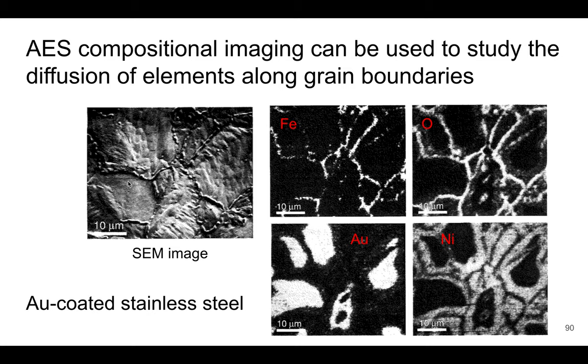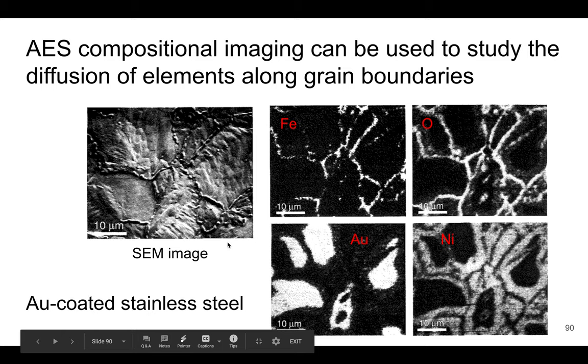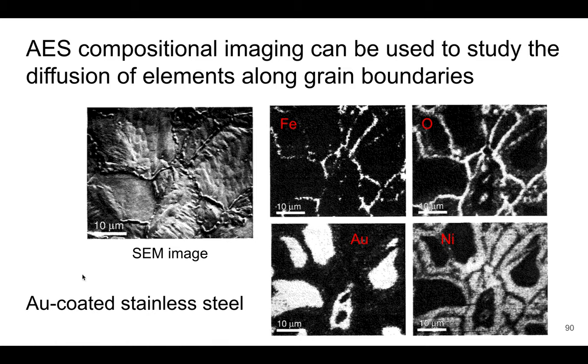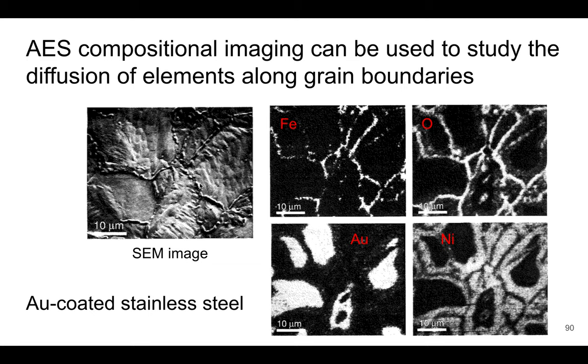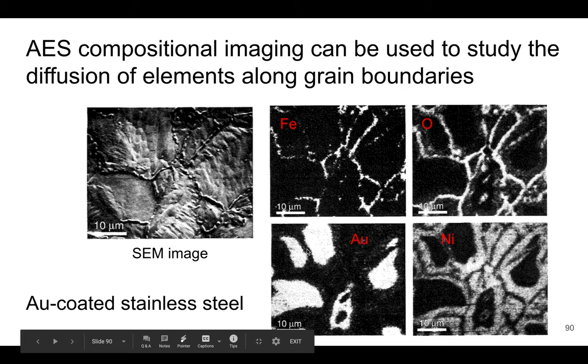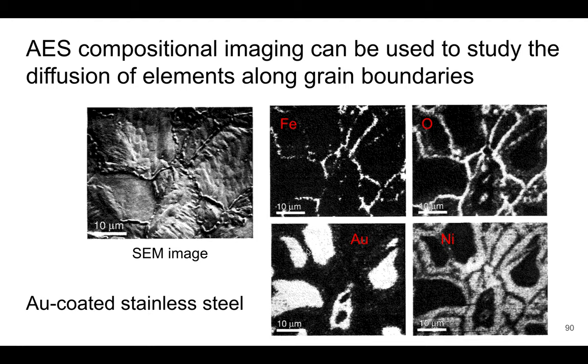We can use this to determine things like diffusion of elements at grain boundaries and different phase regions. Because it's AES or XPS, this is more surface sensitive. With EDS it gives us information about more of the volume of the material, so this can be particularly helpful if we want a more surface-sensitive approach. Here is a gold-coated stainless steel sample, and we see that nickel, oxygen, iron, and gold all tend to go to different positions. Iron and oxygen tend to go to the grain boundaries, nickel is right around them, and gold is in the middle — showing spatial distribution of the elements.